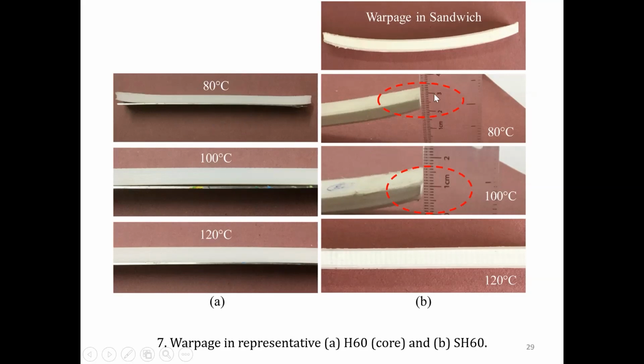Now what happens to the sandwich? Yes, for the sandwich at 60, that is 60% by volume of glass microballoons in HDPE. Here what happened? This warped, you can see this image here, this warped after printing. In other words, during printing until the final top layer, no warpage was seen. Once the last layer's printing was done and the sample was getting cooled in the chamber itself, it lifted up from the ends. And what was the warpage? You can see here, it is 30 millimeters. Then we reduced it to 10 millimeters and then perfectly flat.